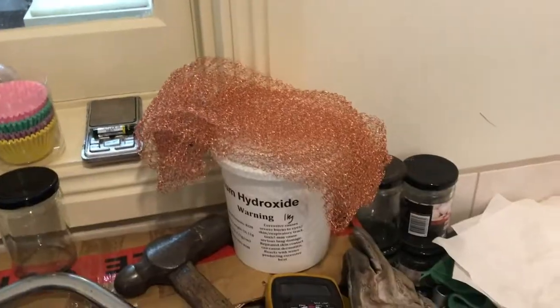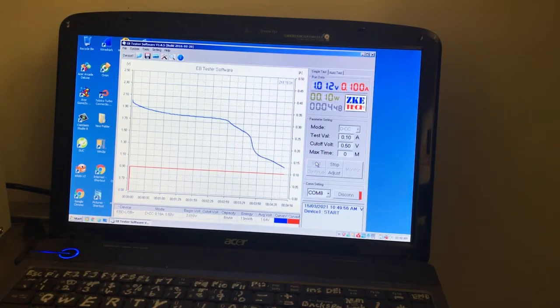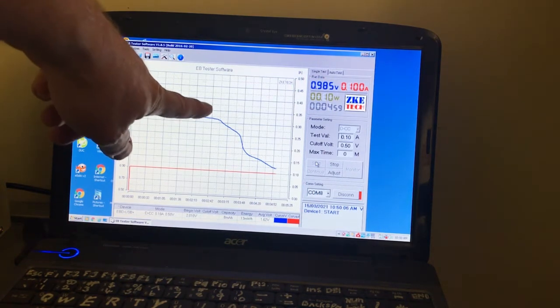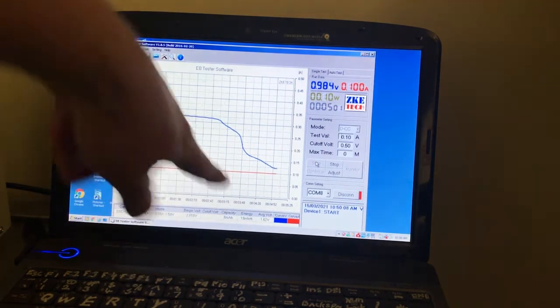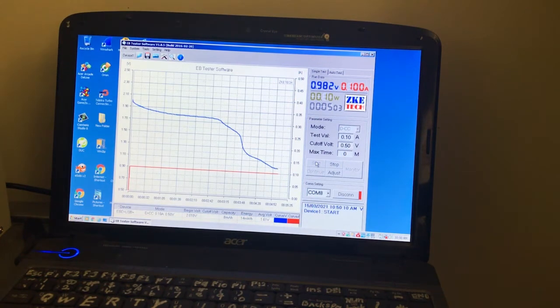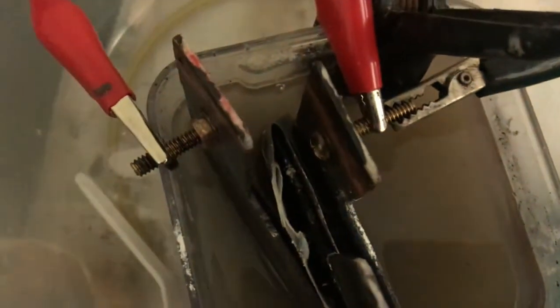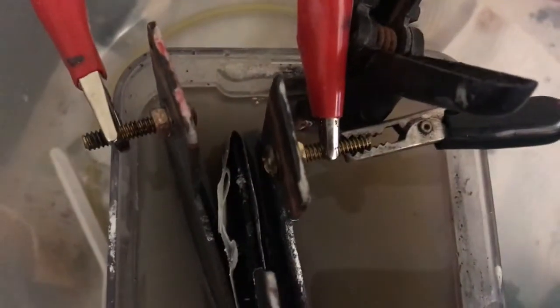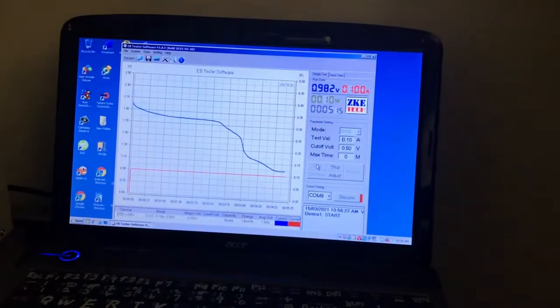Okay, something's causing a major voltage drop in the cell. Some sort of resistance, or maybe the active material on the positive side isn't enough. It goes pretty good for about 2 minutes, and then bloop. I'm pretty sure I looked down in the positive cell and poked around with the tweezers, and the stuff is peeling off, so that's probably one of the reasons.